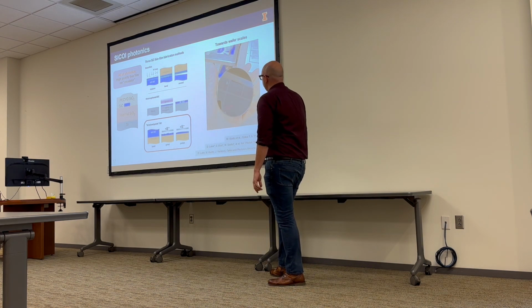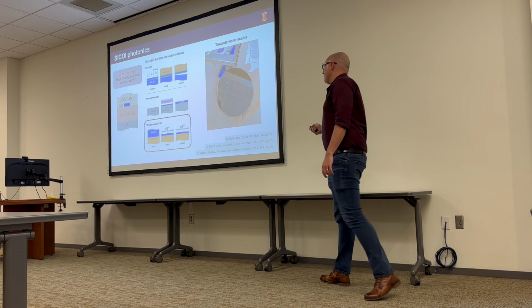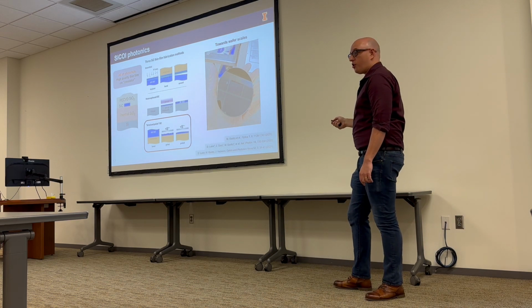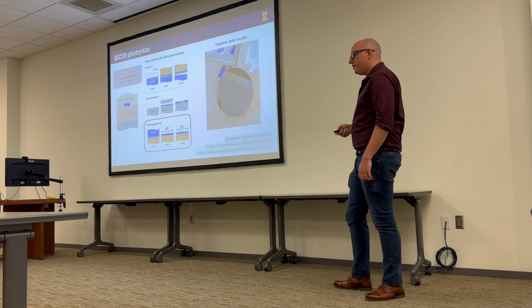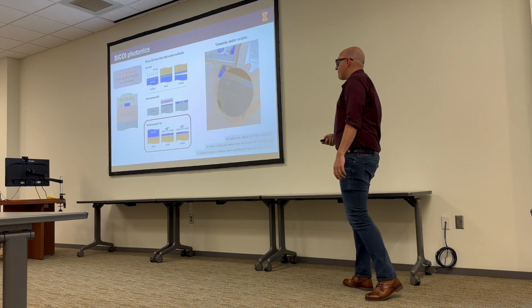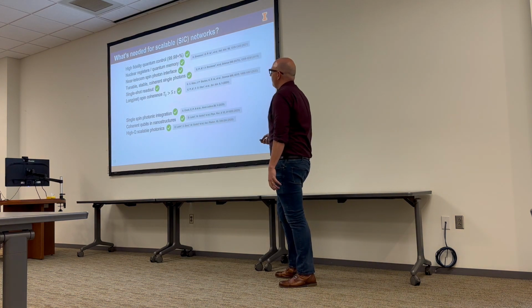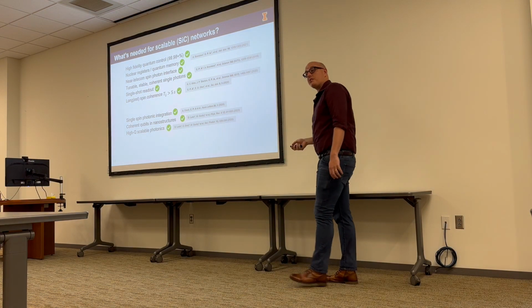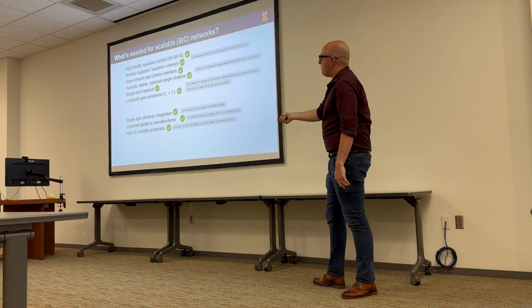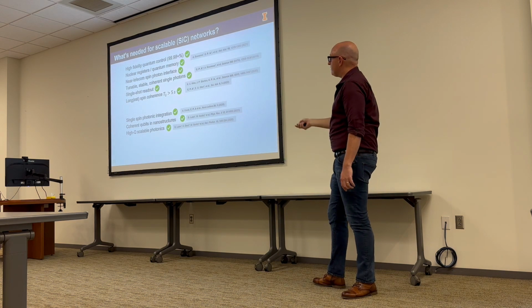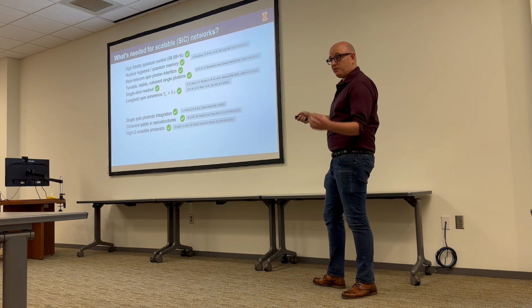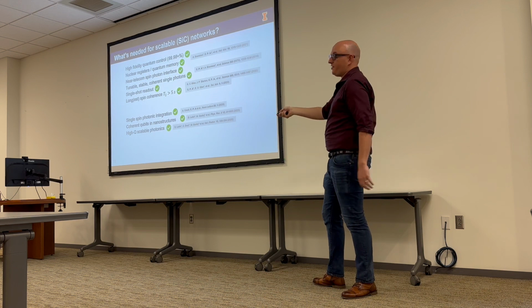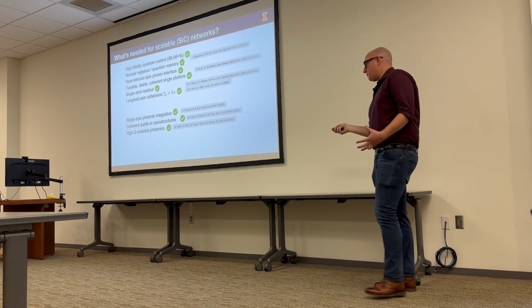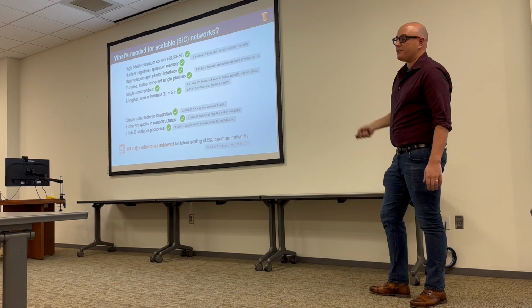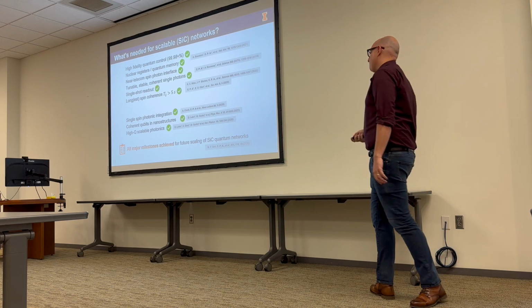Not only that, we're also pushing towards the wafer scale. So here's a photo of me holding a 4-inch wafer of silicon carbide bonded to a thermal oxide wafer. So we can start dreaming of big integrated photonic circuits. And the result of those advances is basically, we think we have all these check marks that we need to do something useful. We have great spins, but we also have great scalable photonics. What I didn't show you is we can also put these single spin qubits inside of those photonics and they remain fairly coherent. So we think we have all these check marks to maybe realizing some of these big dreams for quantum networks.